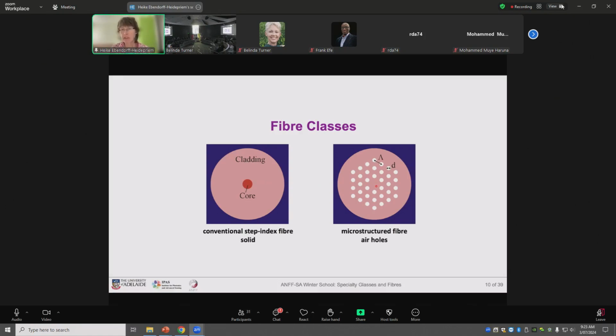One type is shown here, so there's an air hole pattern, and in the center is a missing hole. What it means is that in this region, the refractive index is lower because of the air holes compared to the solid region. So therefore also the light is guided here in the solid core by a modified internal reflection, very similar to solid core fiber.